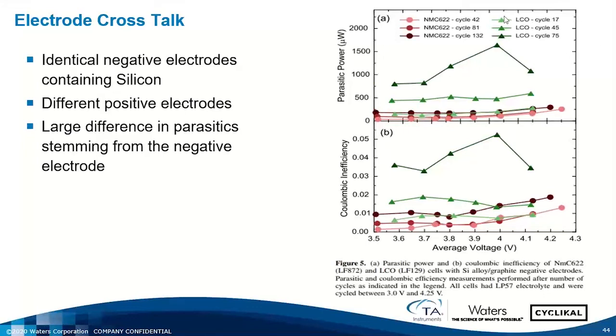We have a lithiated cobalt oxide positive electrode, and we're showing the thermal parasitics at cycle 17, which are down here. We look at it again after cycle 45, and you can see the thermal power has now evolved up to this level, quite high. And after 75 cycles, look at the thermal power now. It's almost 1.5 milliwatts from the lithiated cobalt oxide. But look at the cell that has the NMC 622. Everything's buried down in the bottom here.